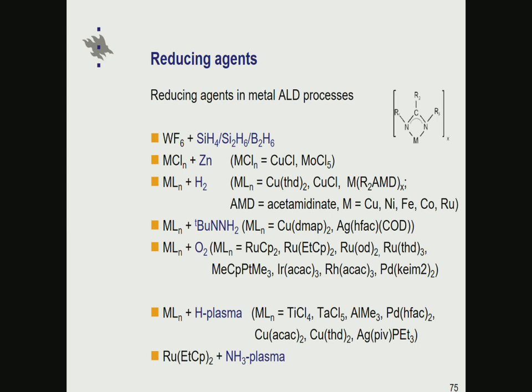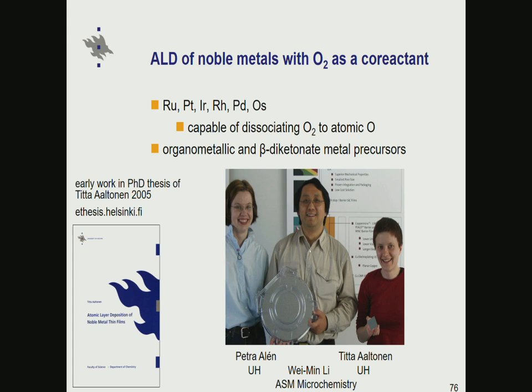Now in the coming slides, I will talk about these noble metal processes. In these noble metal processes, it turned out that by using molecular oxygen, one is able to deposit elemental films, which is a little bit against what you might think. Oxygen should result in oxide deposition, but it doesn't work like that. Well, one explanation for that is that these are noble metals which form low-stability oxides, if forming oxides at all. And these metals have now been deposited using the O2 molecule as the co-reactant.